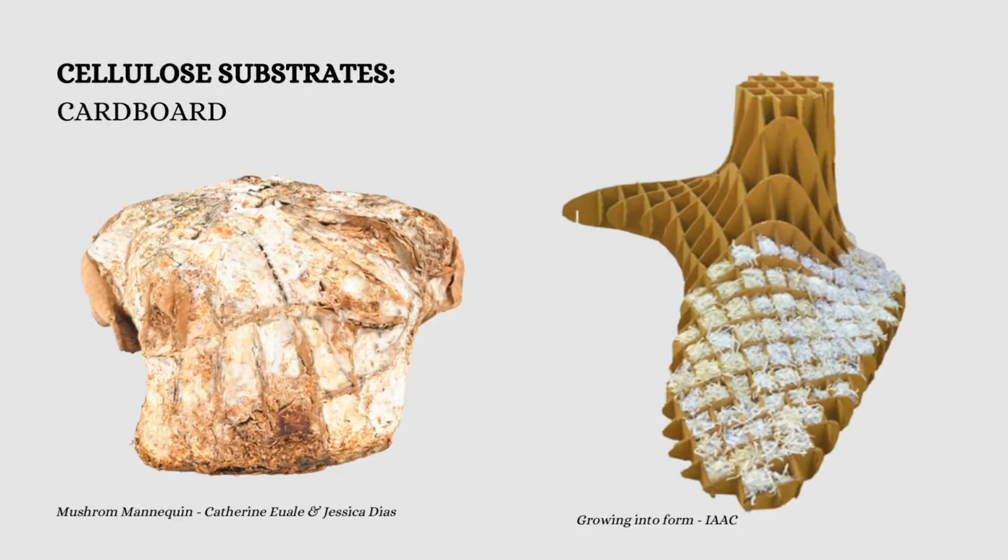And still we got some contamination, or lots of contamination in some spaces. Those are some of the hacks that I have found helpful: to use blue UV light or to use bleach, which is not great, but there's really no way to sterilize the individual pieces before you put this together. Normally, one of the ways that you sterilize cardboard is by boiling, which you definitely couldn't do here because then you would make a paper mache rather than a structure.